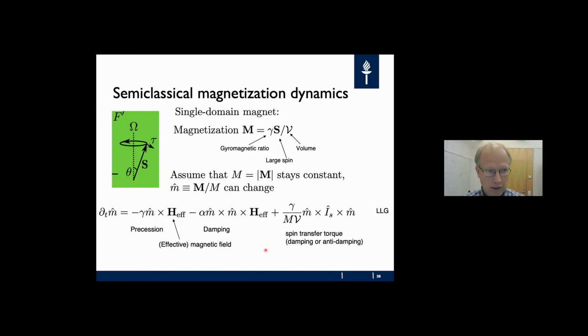The description of the dynamic magnetization is that of the Landau-Lifshitz-Gilbert equation, where you study the dynamics of the magnetization vector, assuming that only the vector direction can change in the dynamics. The Landau-Lifshitz equation contains the first term, which describes the precession due to an effective magnetic field. This term here is the Gilbert damping term, which damps this precession.